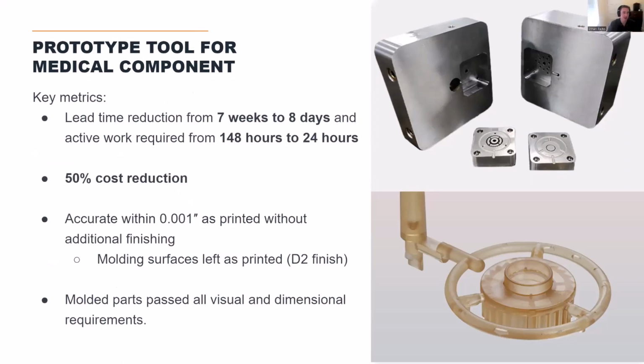Some of the key metrics for this company, they were able to reduce the lead time here from 7 weeks down to 8 days. They said they would have had to outsource this tooling, which would have taken them 7 weeks to produce, but now they're able to do it in-house in just 8 days. The amount of active work from tool making went from 148 hours down to just 24 hours. So obviously you can already see how this is clearly accelerating their product development, to be able to get functional end-use parts in just 8 days out of a tool steel tool. They also saw a 50% reduced cost compared to outsourcing this tool, and the entire tool was accurate within a thou without any additional finishing.